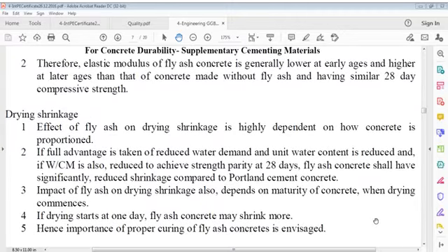Therefore, elastic modulus of fly ash concrete is generally lower at early ages. Elastic modulus of fly ash concrete is generally lower at early stages and higher at later ages than that of concrete made without fly ash and having similar 28 days compressive strength. This means elastic modulus of fly ash concrete is lower at early ages, you can say 28 days age, and higher at later stage than that of concrete made without fly ash and having similar 28-day compressive strength.